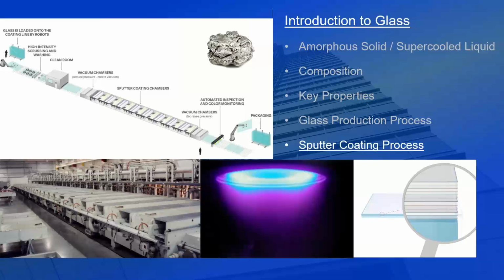The first thing that happens here is that glass, after it is cooled and cut to the size required for the fabricator, or required as the stock size, gets cleaned, because any debris, dust or particles on the top surface of that glass could impede the application of the Low-E coating. So the glass gets cleaned, then it gets slowly introduced into vacuum chambers. It's essentially a step down process, because the conveyor belt system that moves the glass through the process doesn't stop. The glass is constantly moving. Each chamber reduces the atmosphere around the glass by about 1/3.